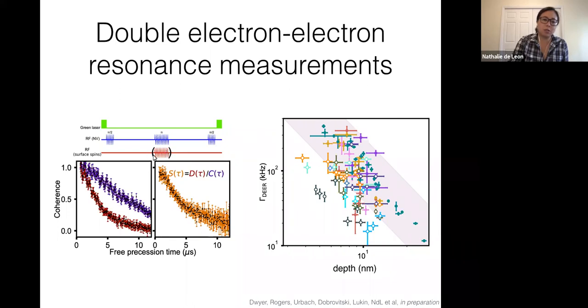But then what we can do is bring in a second microwave tone that selectively addresses this population of surface spins, which are spectrally separate from everything else because they're g equals 2, spin 1/2 electronic spins. And basically when you apply this pi pulse, what you effectively do is cancel out the noise from everything else with this Hahn echo sequence, but then you continue accumulating phase from these other surface spins. So you isolate the contribution of the surface spins to the decoherence of the NVs.